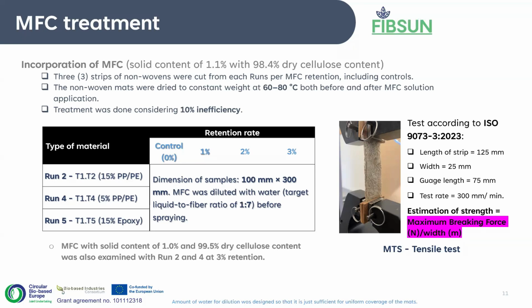Nonwovens are typically bulky. MFC has very low solids content, but the emulsion effect makes it a bit less easy to combine with nonwoven. So we examined the incorporation of MFC at the lab scale, and the goal for the entire MFC incorporation is to be able to spray MFC along the line in the industry onto the nonwovens. But in the lab, what we did was we had to pre-dilute the MFC to enable adequate coverage across the nonwoven. And of course, it means we needed to introduce water again.